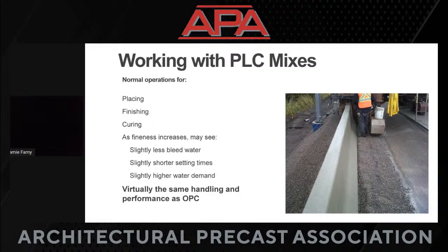So let's talk about, again, this is designed to be drop-in ready. This is a technology, a one-to-one replacement, swap it out, you're good to go. You have the same operations for placing, for finishing, for curing. Now with curing, I will mention, as you see that fineness increase, because these are finely ground cements, you might see a little bit less bleed water. Maybe you can get on your slab sooner. You might see a little bit of a reduction in setting times, because again, that strength is kicking off pretty quick. You might see a little higher water demand.